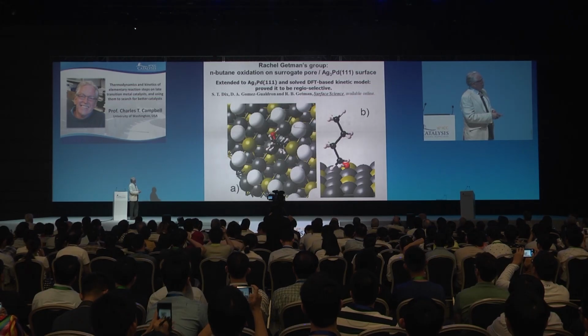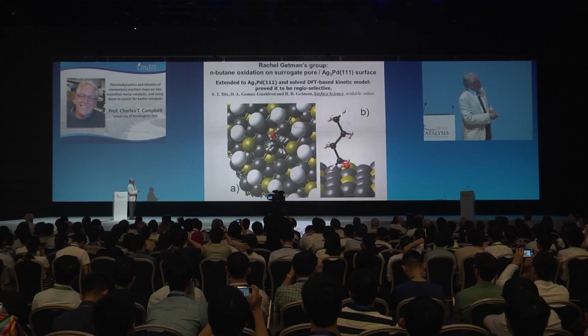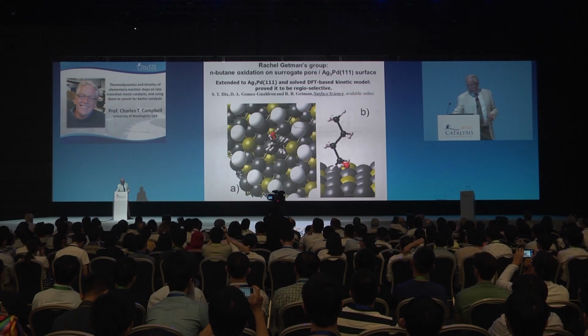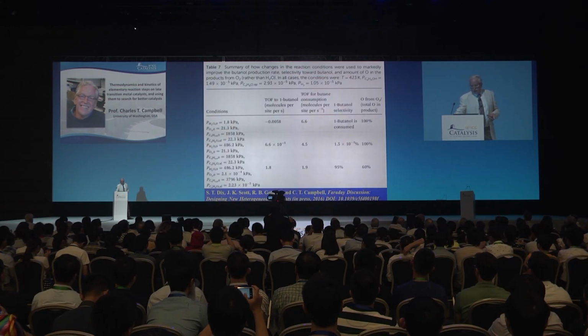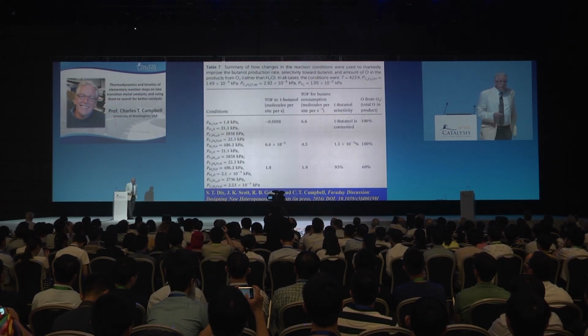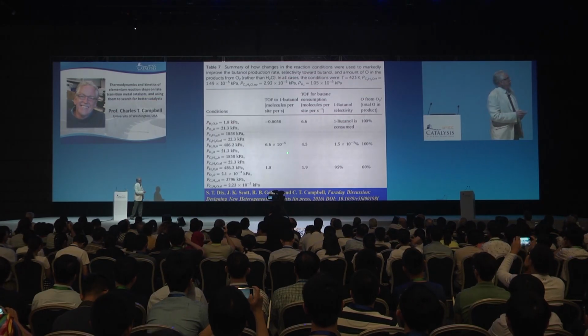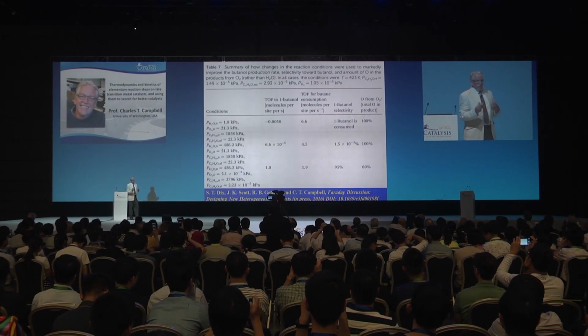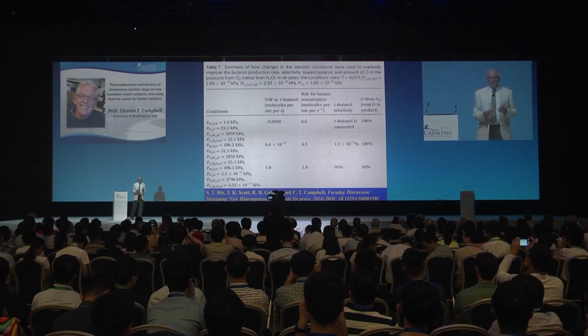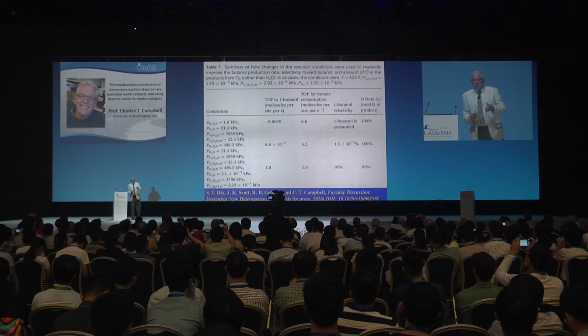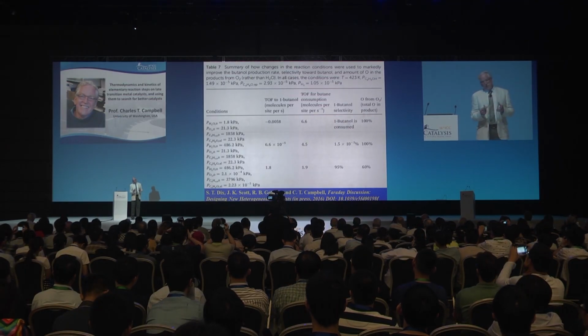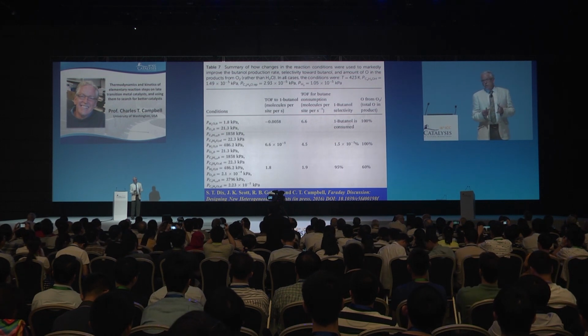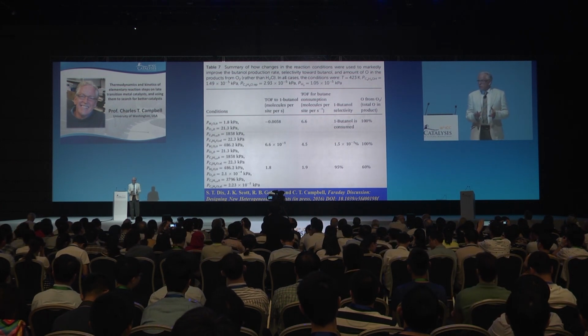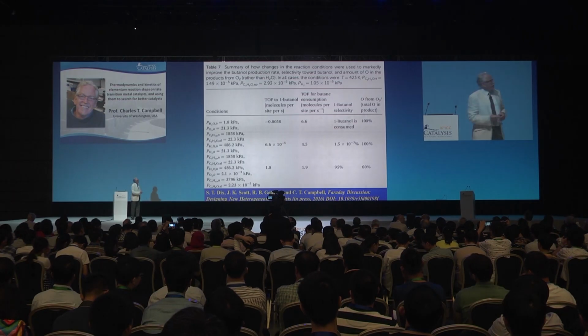Here's a cartoon of the surface that we studied together with Rachel Getman's group for this. It's a silver palladium alloy trying to make 1-butanol out of butane. And what we did is we looked at the degrees of rate control, and the original plan was to try to find better catalytic materials using something I'll talk about next. But what we discovered is when we looked at the degrees of rate control, there were obvious ways to greatly improve the catalyst by just changing the reaction conditions.